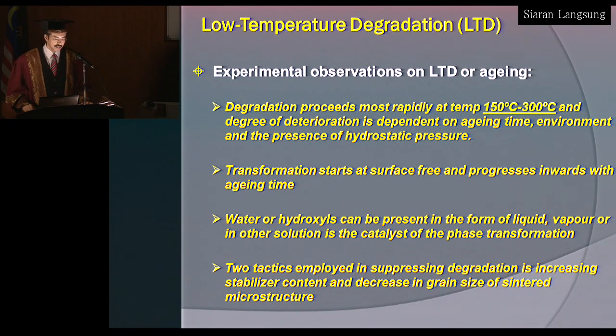And the degree of deterioration is dependent on the aging time, how long it has been exposed, the environment, and also the presence of pressure, hydrostatic pressure. So that's where the steam comes in, because with steam, you have water and you have pressure. Now, transformation normally starts at the surface, and it progresses internally over time. Now, water or hydroxyl can be present in the form of liquid, vapor, or in other solutions, such as in acid, as the catalyst of the phase transformation. So water has been identified as the culprit.